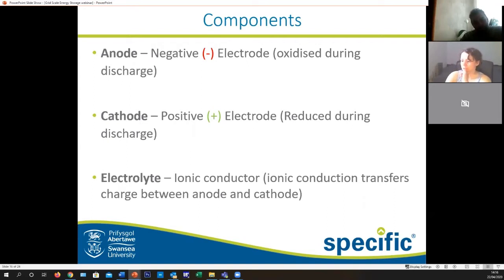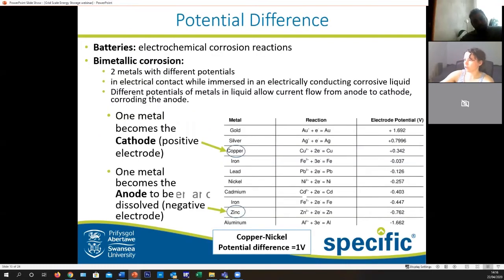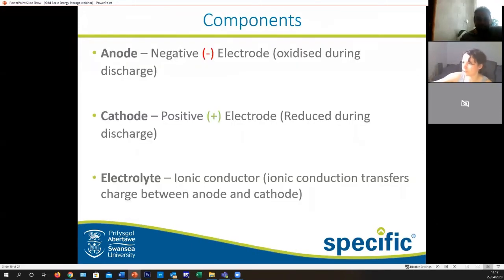There is an example of where you can get batteries when you really don't want them. In a hypothetical scenario — an underground tunnel somewhere in the world which was recently electrified — there was a problem because two materials with very different electrochemical potentials were used in a salt water environment, and they were very surprised when parts of the tunnel started rusting within a few months. Always beware — you can make a battery even when you're not expecting it.